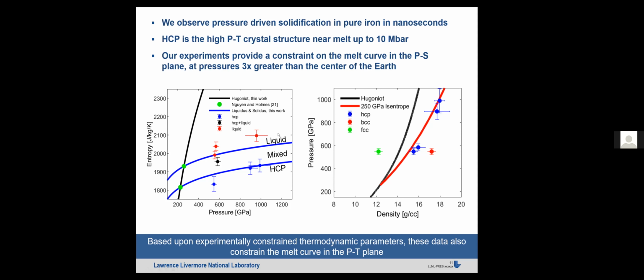Thanks, Steve. So two questions there. I think there are two aspects to thinking about the shear stress. One, which we talked about when answering Philippe's question, is: does the shear stress create any work which increases the entropy that we are not considering? Looking at the data for all but this lowest entropy point, which has a significant amount of compression in the solid phase, even using the models, the amount of entropy generated is still within the error bars here. For every other point, the amount of plastic work heating due to shear stresses would very negligibly increase the entropy. And so that's why we did not include it in our additional entropy in these points.